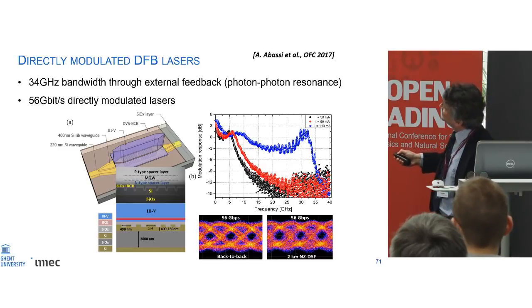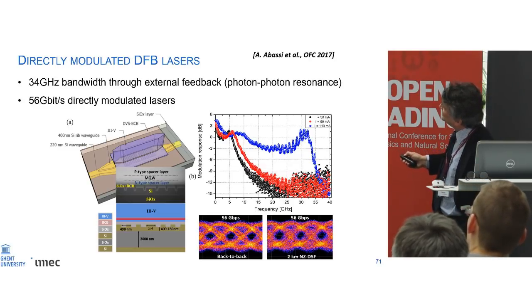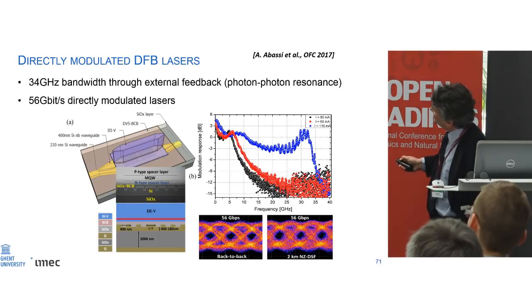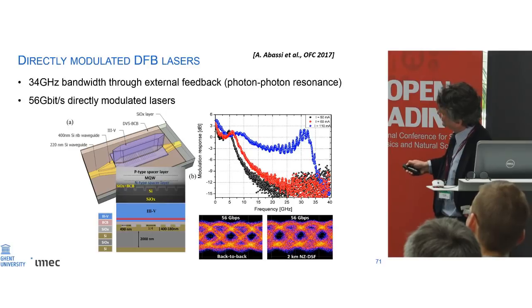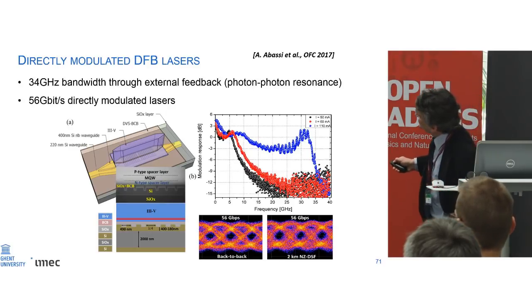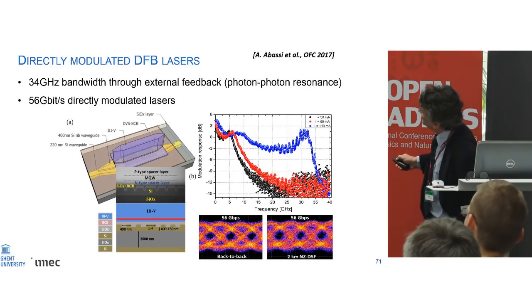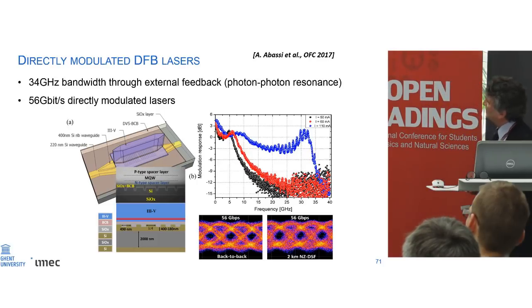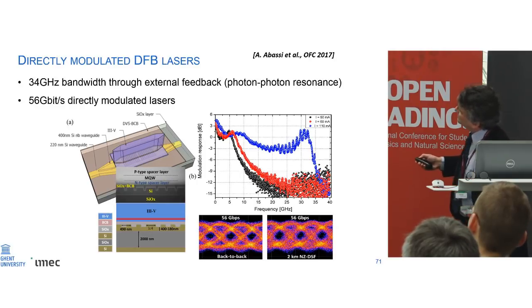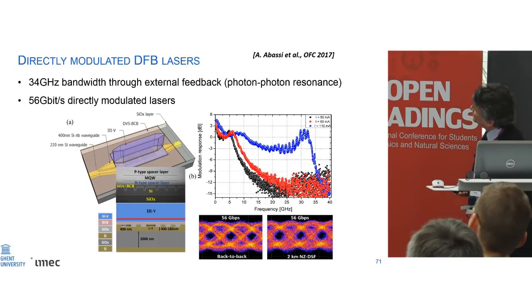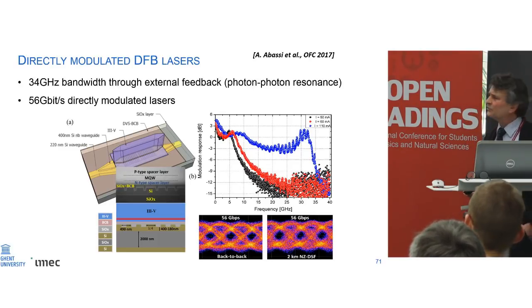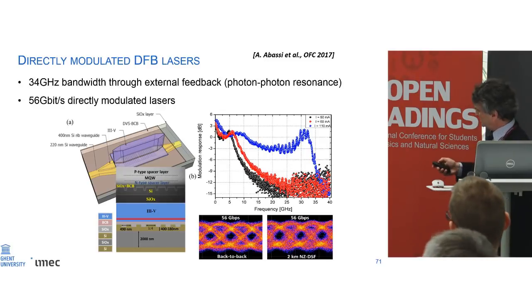For example, here you see an example of a directly modulated distributed feedback laser. The yellow here is silicon. The bluish here is the III-V. The grating, which you invariably always have in a DFB laser, is defined in the silicon. And you see indeed these tapering structures that make light move from the silicon level up into the III-V level and back into the silicon level. And this works really very nice, and in this case, we achieved even direct modulation bandwidths up to 56 gigabit per second, which is actually not so easy to do in a III-V only DFB laser.